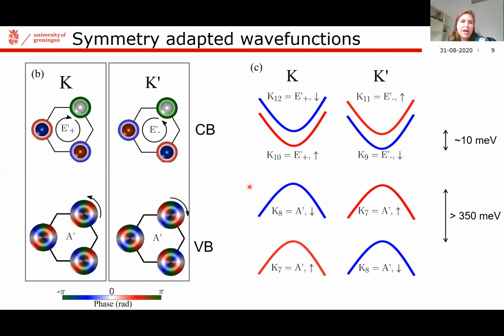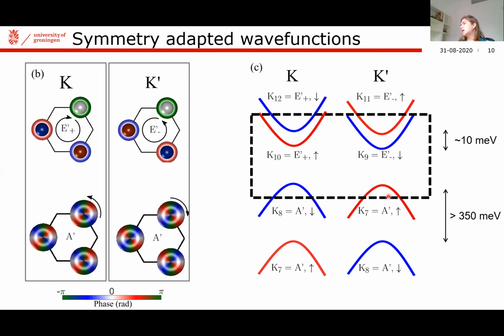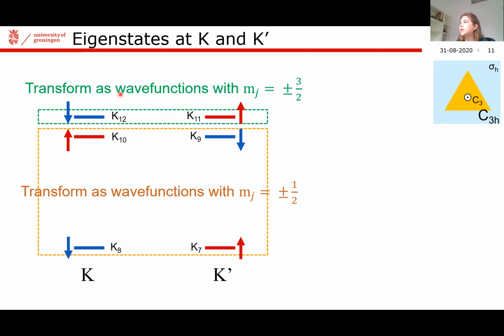Now, like I mentioned also before, I'm mainly interested here in low energy processes, so processes that we would observe in transport. And for that reason, since this splitting in the valence band is so large, I will from now on disregard these lower levels here. Also, from now on, because I'm interested in the symmetry of these states really at the edge of the bands, I will represent them as states rather than bands. And what I want you to notice, although I have written down all the irreps explicitly, the only thing you need to remember is that these states that I circled in green transform as states with angular momentum plus or minus 3/2. Whereas the states that I circled in orange transform as wave functions with angular momentum plus or minus 1/2. So this gives us now all the symmetries that we need to figure out the selection rules.